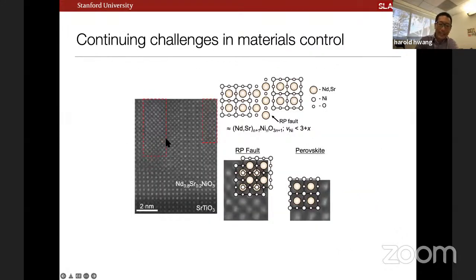If I look in detail at one of these boundaries, sorry if these boxes are actually making it harder to see, but let me just illustrate it here, that we have a fairly generic instability to making these so-called Ruddlesden-Popper-like intergrowths, right? So it's this motif that I showed you in this layered family of building blocks. And of course, you can ask, well, isn't this just a matter of delivering the right stoichiometry? But we think it's much more than that.